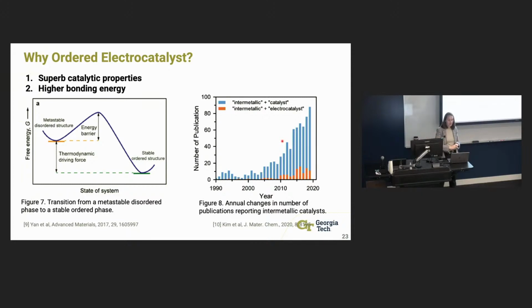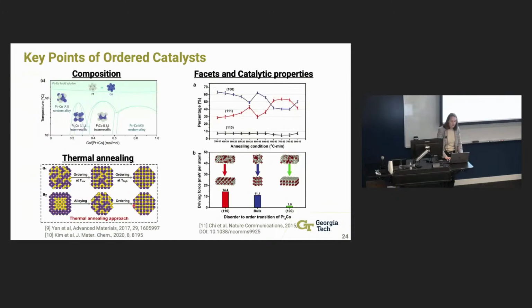And they really, basically you have a metastable disordered phase, but then a really ordered stable phase, if we can get them into the ordered phase. And this can be a potential improvement, especially in stability and durability of your catalyst.